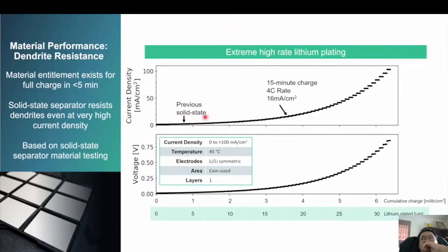So many solid state efforts could do south of 1 milliamp per centimeter squared, or up to about 1 milliamp per centimeter squared. To get to the 4C charge rates that I described earlier, that's 12 to 16 milliamps per square centimeter, depending on cathode thickness. We went all the way to north of 100 milliamps per square centimeter across the separator without failure. And so then this is showing the corresponding voltage that develops across this lithium-lithium cell.